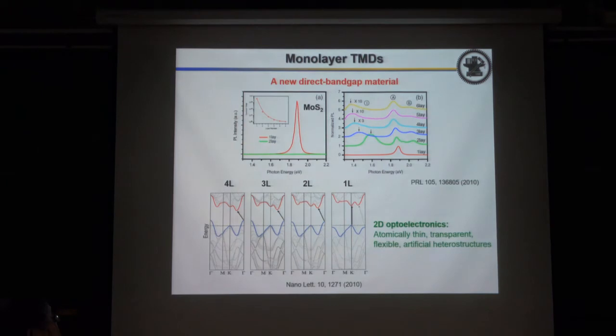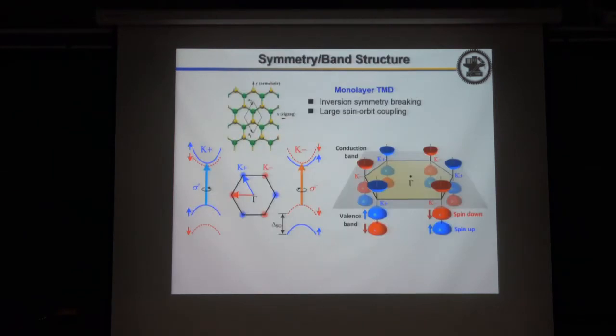So the TMD materials, 2D semiconductors, also have some other interesting properties. For example, when they are multilayer, they are indirect semiconductors. But when they are reduced in thickness to only one monolayer, they become direct bandgap materials. And they also have a very unique electronic band structure. They have conduction band and valence band minima and maxima at the K valleys, and they have some spin splitting, some spin structure, which is reversed in different valleys.